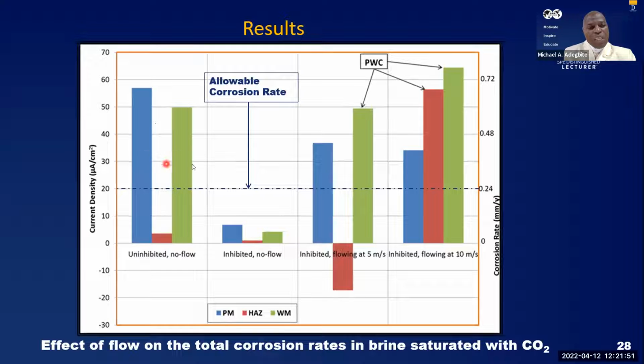Here, in this first one, preferential weld corrosion is only when the corrosion rate of the parent metal is less than that of the heat affected zone or the weld metal. So here in no flow and uninhibited, we can see that the corrosion rate of the parent metal is higher. So there's no cause for alarm in this instance. That is no preferential weld corrosion. But something of note is that with inhibitor, we can see the corrosion rate. The allowable corrosion rate is 1/4 millimeter per year. That is the usual corrosion allowance. When we say corrosion allowance, it makes provision for the fact that corrosion rate could be a maximum of 1/4 millimeter in a year, uniform.